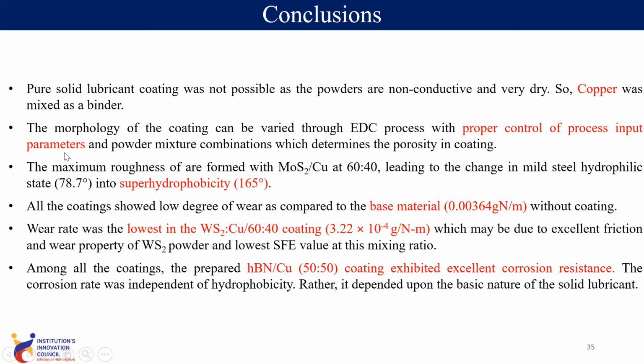As we have seen, at a large peak current, a large coating thickness was obtained. So we can control the coating characteristics by controlling the process parameters, which also determine the porosity in the coating, because a large amount of tool erosion results in a large amount of deposition, and a large amount of tool erosion is possible at high current. Maximum roughness was obtained for the MoS2 copper coating, as we have seen a large amount of nodular protrusion on it, resulting in a large contact angle of 165 degrees.